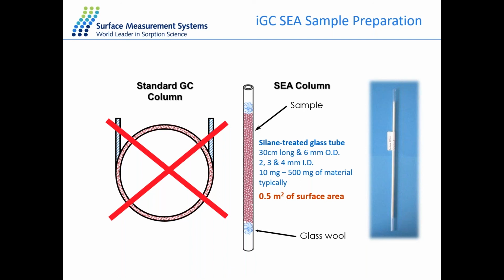Great, thank you. A question here from Moshem Gao. They ask, how much sample should you be using for an iGC experiment? So the sample is typically based on the BET surface area of your material. So if you have quite a low surface area material, about 1 meter squared per gram, you may need about 500-600 milligrams of your sample. However, if you have a sample which has a slightly higher BET surface area, so about 100 meters squared per gram, you would need roughly about 10 milligrams. So it does depend on the rough estimate of the BET surface area.